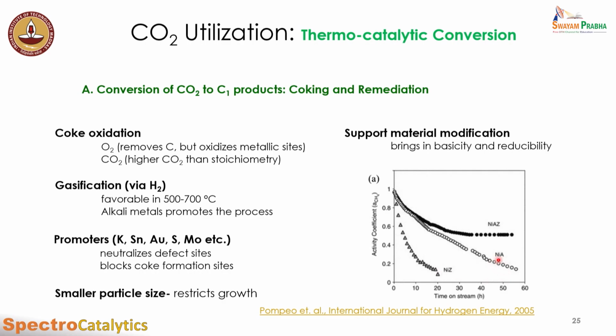If we go to nickel on alumina, the deactivation is slower, but it achieves the same final activity at a longer time. But if we mix zirconia and alumina, we get higher dispersion of nickel as well as a proper balance of acid and basic sites, such that there is some initial deactivation, but after a certain time the catalyst performs in a stable manner—there is no more deactivation.